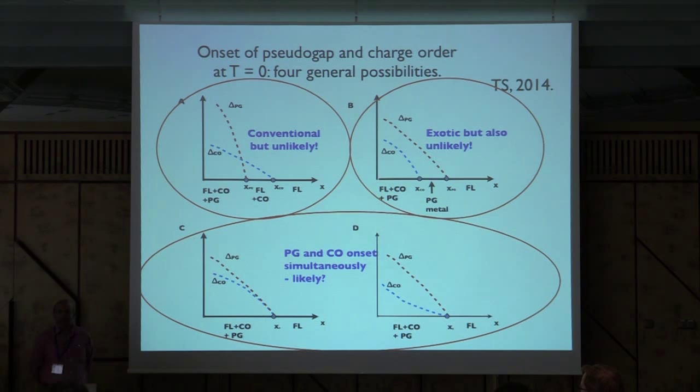So on the overdoped side, we can ask to what extent it is a Fermi liquid. And that's a great discussion to have in light of your findings over the years. It's not that much of a bad actor, because as you showed, it shows nice quantum oscillations with an area that matches the photoemission Fermi surface beautifully. As you also know, it shows a Wiedemann-Franz law that's obeyed to within 1%. So it looks like it's a good boy or good girl that's occasionally misbehaving. It has one bad feature, that there's this small linear resistivity in a narrow temperature range at low temperature. So I'm willing to overlook that for the time being. It's only mildly mischievous, in your language. Everything else is really bad.